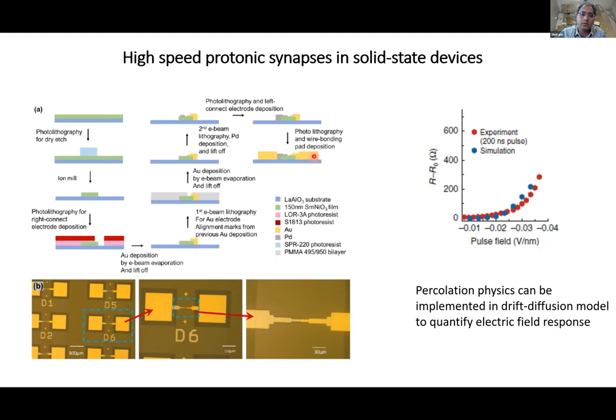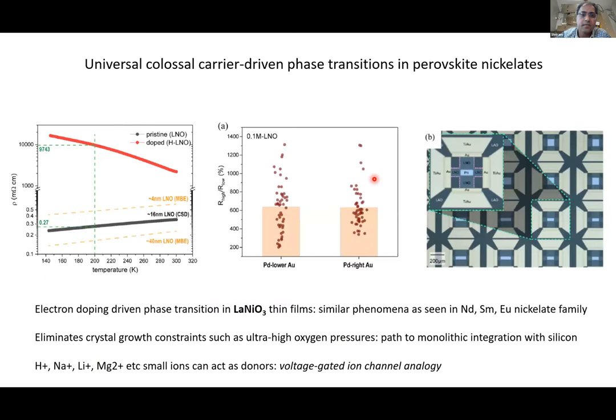So because you are working with protons, which is basically next to the electron, it's the lightest or the smallest dopant perhaps. And so we are able to move these very fast, get responses down to nanosecond timescales. And also you can fabricate these structures by lithography fairly carefully. And so you can sort of work with all solid state devices.